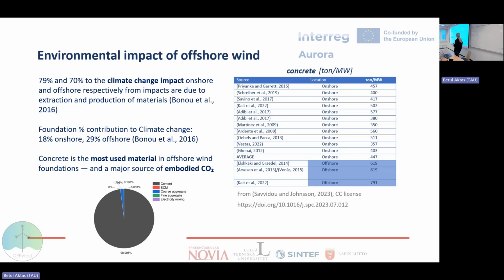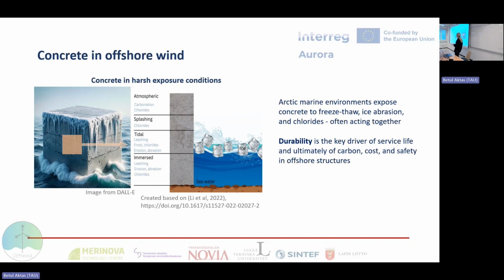So if we look at this, concrete is the most used material in offshore wind foundations. And because of the Portland cement production, and Portland cement is still the main binder used in concrete, it produces a lot of CO2 because of the clinkering process. So what can we do to decrease those CO2 emissions? We can use, for instance, alternative binders, but there are other aspects than just replacing cement that we should take into account when we look at the offshore wind structures.